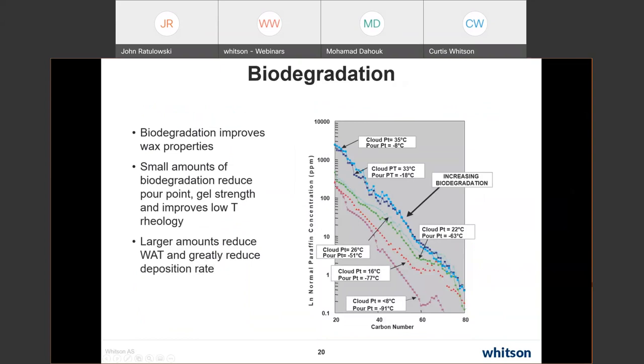All right, one final thing to note on wax that is very important is biodegradation. Particularly if you have biodegradation in the reservoir, and you may have variable biodegradation in a reservoir where a lot of it's occurring at the oil water interface. And as you get away from that, you may see less. It's important to know that that will impact your wax properties quite substantially.